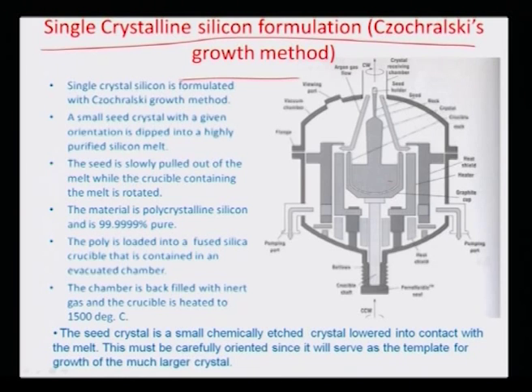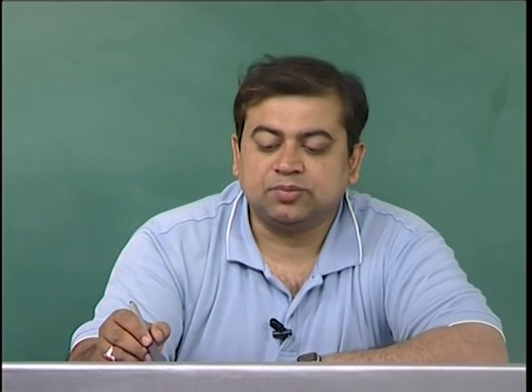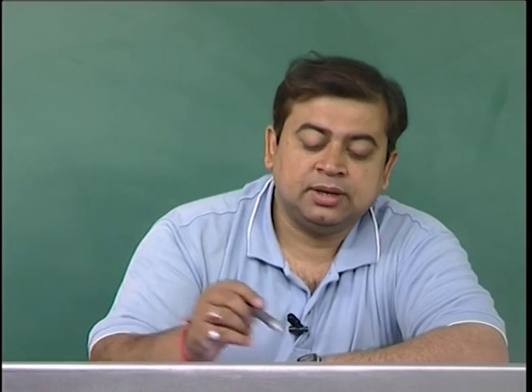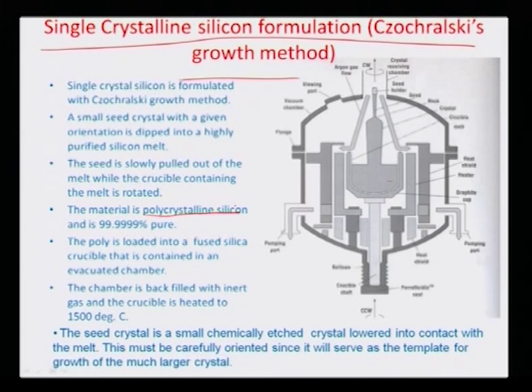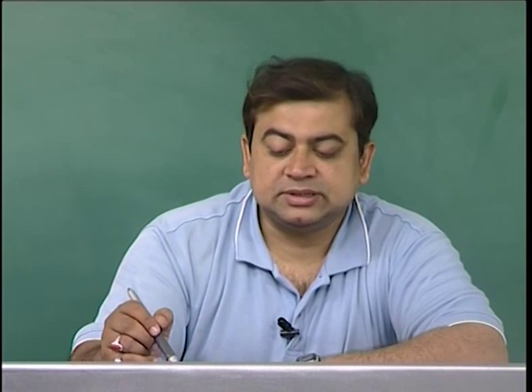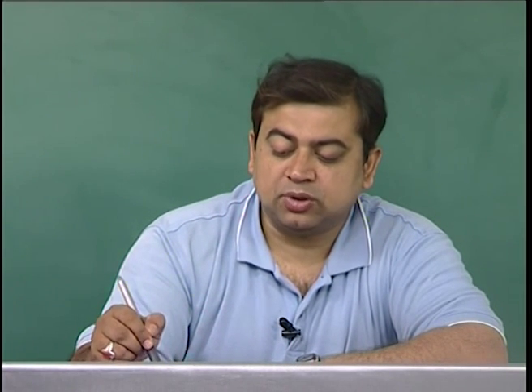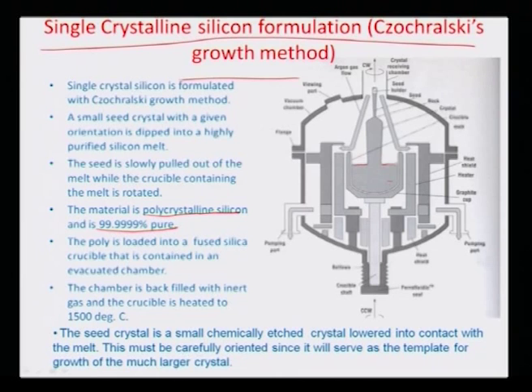And in context of that, the most important method that is illustrated in literature very often is the Czochralski growth method, in which silicon can be obtained from 99.9999% pure polycrystalline silicon, which is fused. And this fusion process is by thermal means. There is a crucible which is indicated here in this figure, which comprises a central cavity, and this cavity, as I am illustrating by this border here, contains the polycrystalline silicon fused material.